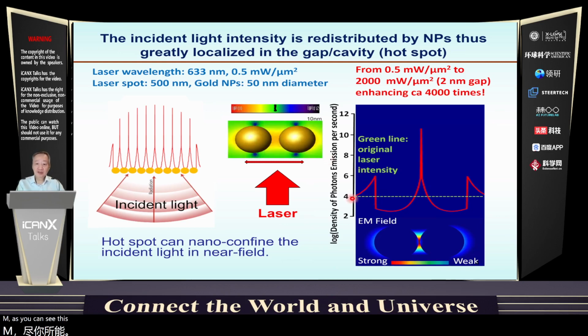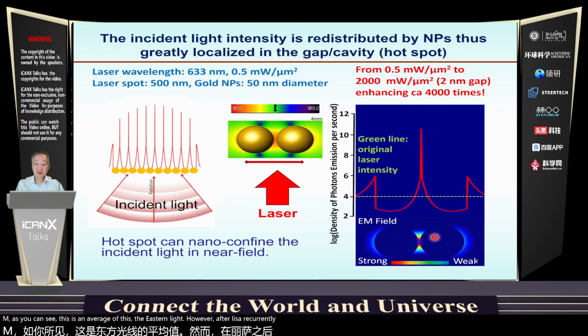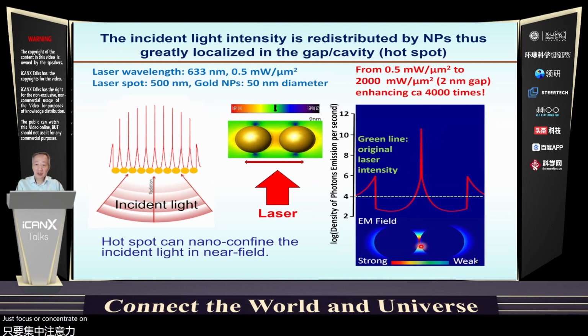As you can see, this is the average of the incident light. However, after this redistribution, we can see light focus or concentrate sharply at this gap of the nanoparticle. As you can see, the intensity of the light can increase from 0.5 milliwatt per micrometer square to 2,000 milliwatt, 2 watts. It's critical. It's really amazing.